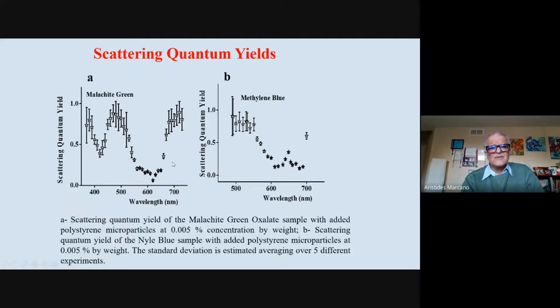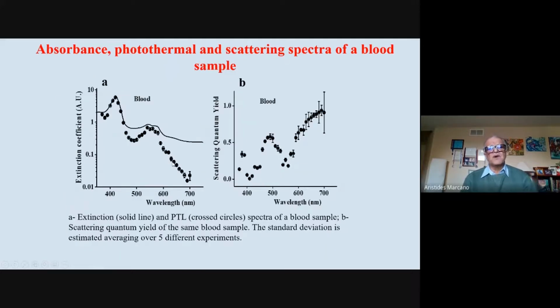Good. Here I did an experiment with blood. Blood actually produces some differences in the thermal lensing, because blood is a complex sample and it has a lot of scattering and so on. When you do absorbance and compare it with thermal lensing, you have a big difference. But now you subtract them, and you get the scattering spectra. You see the scattering spectra produces some different behavior and have different peaks that maybe you can use for a different characterization of blood or other complex samples like blood, using this thermal lensing spectroscopy.